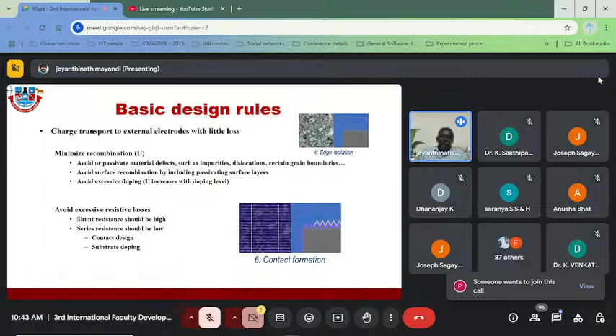And the next thing is, once the electron hole pairs are separated, we need to capture the electrons efficiently and transport them to the electrodes. To do that, we need to minimize the recombinations, avoid or passivate the material defects, impurities, dislocations, and excessive doping, and also avoid shunt resistance. So these are all the things one has to do to have an efficient charge transport to the external electrodes. And you could see this video, and you will have an idea about that.